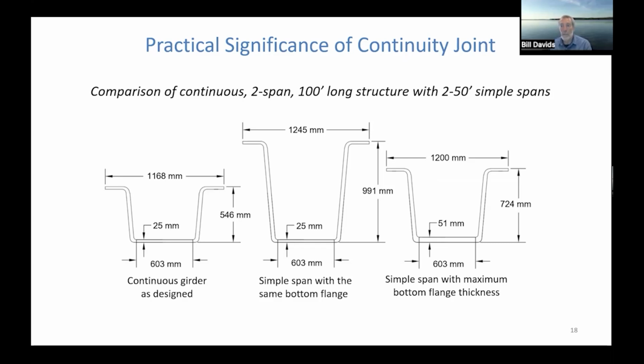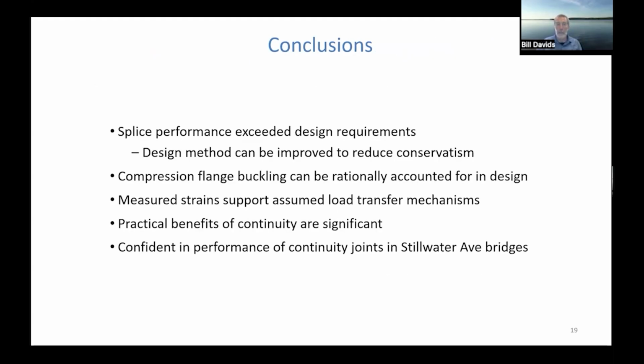And then if we allow the bottom flange thickness to increase up to the maximum practical value of 51 millimeters or 2 inches, that's about all you can infuse effectively, you would still have to increase the depth of that section for a simple span from 546 to 724. Again, it will be a deflection-driven design. So the benefits of that live load continuity are very clear. And we're hopeful that this is going to open up new markets for the CT girder in its use in continuous structures. And the Stillwater Avenue Bridge is going to be the first test case of that.